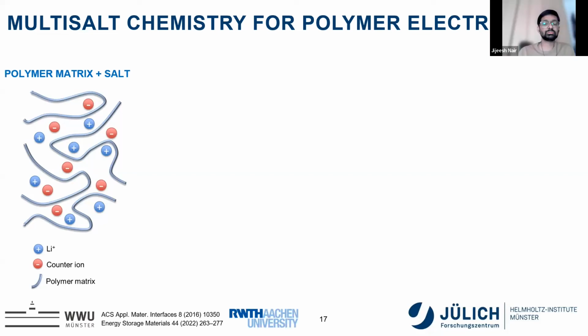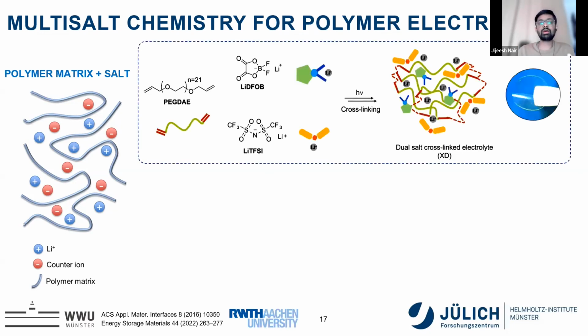Yeah, thank you. I will give only one example of one of my recent works, where if you compare with a polymer electrolyte, you have a polymer electrolyte where you have a lithium salt and polymer. But in this case, we are using multiple salt systems or multi-salt chemistry, because you can really fine tune the same polymer matrix with multiple salts to get a much improved product. It has been least applied. It is most successfully applied in liquid electrolyte, but very few attempts have been made in the solid state system or polymer electrolyte.